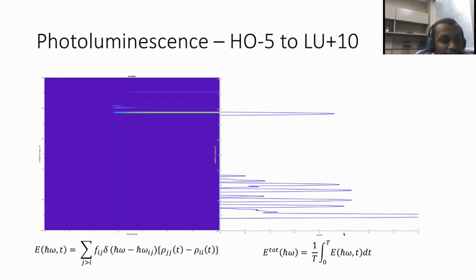It's similar, but the way that the calculations are set up, there's no population decay. If that makes sense. So it relaxes to the lowest excitation energy, but it just keeps counts for where photoluminescence would come from until the simulation stops. So it's analogous to the lifetime measurements, but it's not exactly that.